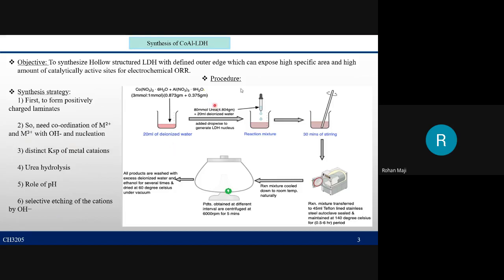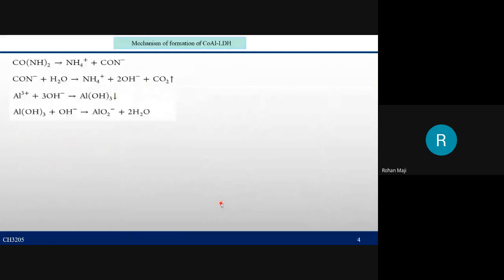So they followed the co-precipitation method. Accordingly, they first mixed equimolar amounts of cobalt nitrate and aluminum nitrate with urea solution, stirred, passed to an autoclave for a 0.5 to 6 hour period to maintain high temperature, and centrifuged for separation. The mechanism is as follows.